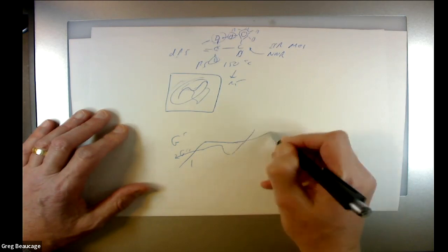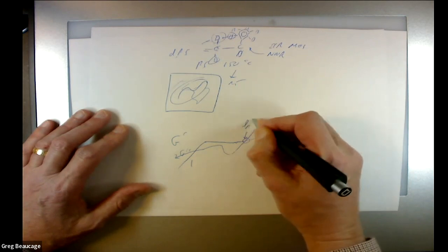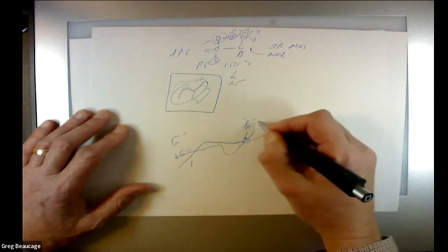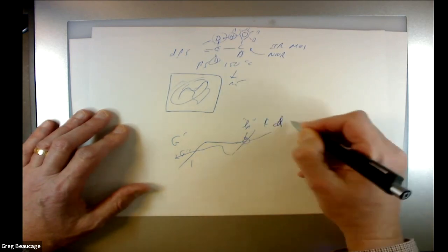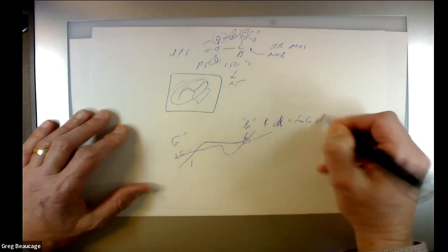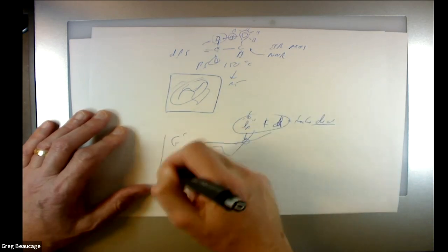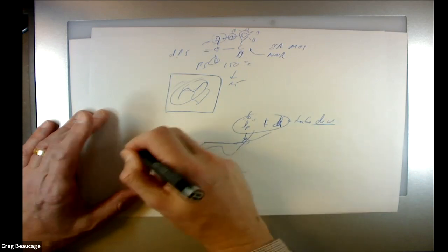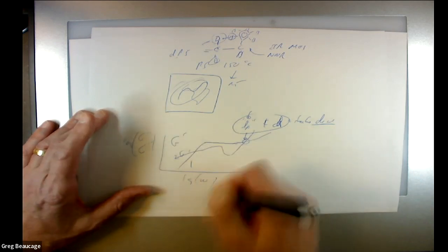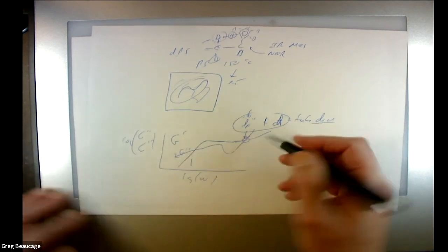And this guy goes up over here. There's another crossover, and that's kind of at L_P. That has to do with two things, L_P and the tube diameter, D. So you can kind of get the persistence length from that G prime, G double prime, omega log plot. I mean, they think they can.